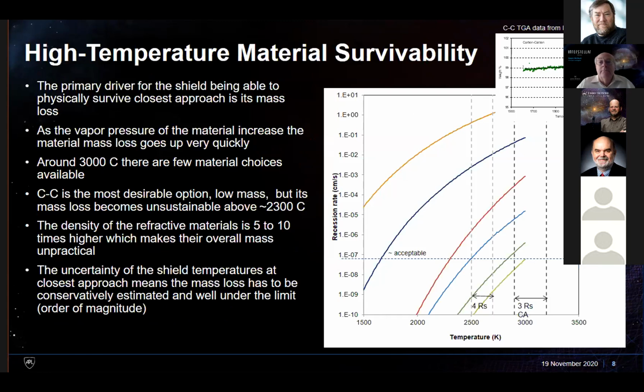So we'll talk about material survivability. The primary driver for the shield is mass loss. At these temperatures, the vaporization of the material is going on and is causing them to lose thickness and lose mass. There's a bunch of curves up there for these materials. There's a legend. I'm not sure why it got dropped off, but the legend has one more. There are 6 lines here, and there's only 5 lines shown. The bottom legend is tungsten.